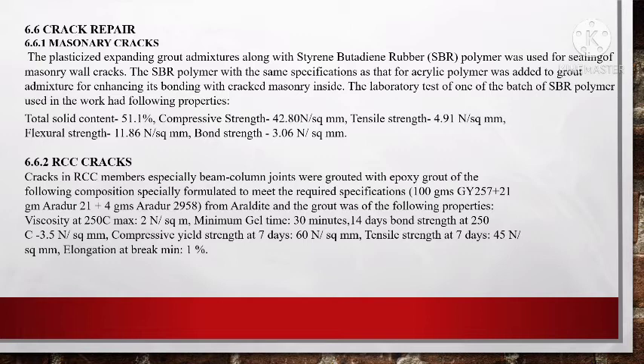Cracks in RCC members, especially beam column joints, were grouted with epoxy grout of the following composition, specially formulated to meet the required specification from Araldite, and the grout had the following properties: viscosity at 25 degrees C max is 2 Newton per square meter, minimum gel time is 30 minutes, 14 days bond strength at 25 degrees C is 3.5 Newton per square mm, compressive yield strength at 7 days is 60 Newton per square mm, tensile strength at 7 days is 45 Newton per square mm, elongation at break minimum is 1%.